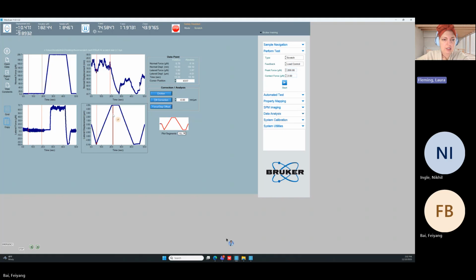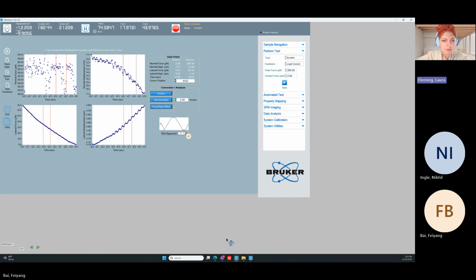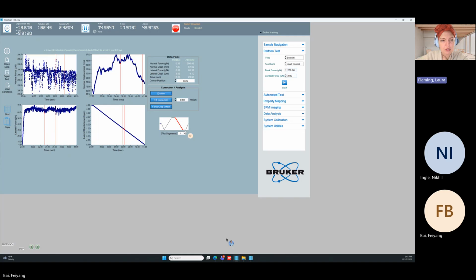We can click through and look at these different scratches and see what the displacement looked like. This is during the actual scratch, in contact with the sample. You can see that we have our normal force and a pretty constant lateral force too. Looks like we're getting some bumps in the normal displacement. I'm wondering if we had some buildup from the aluminum. We can look at it as a whole and pick certain segments. This is the segment where the scratch actually occurred.